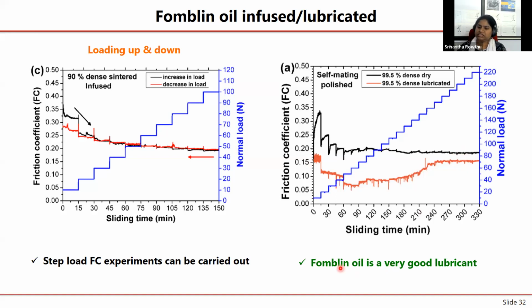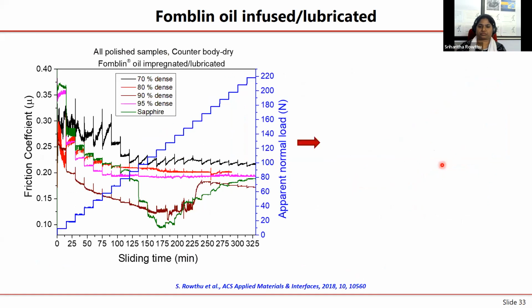So Fomblin oil is definitely a good lubricant, and it has certainly reduced the friction coefficient for just the lubricated situation. Remember that we wanted to compare our infused samples with the lubricated samples also. Okay, so in the lubricated stage itself, it was able to decrease the friction coefficient. Now let's continue, and then we can basically do it for all the substrates.